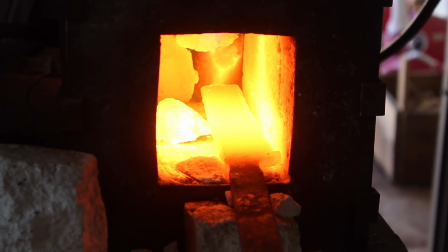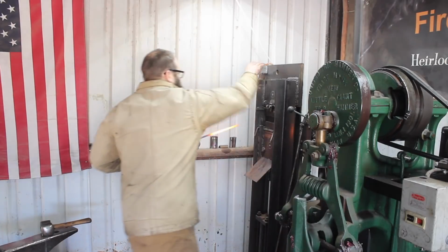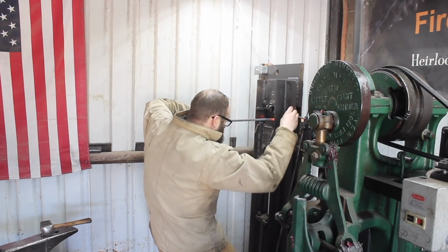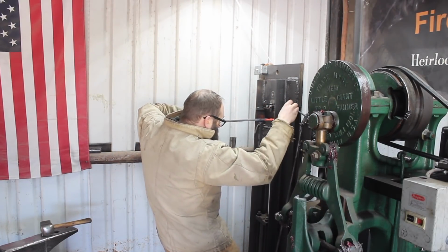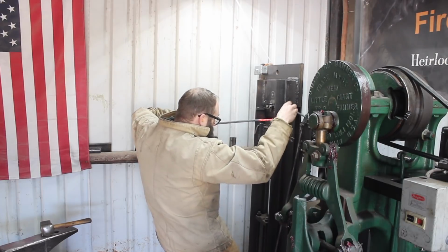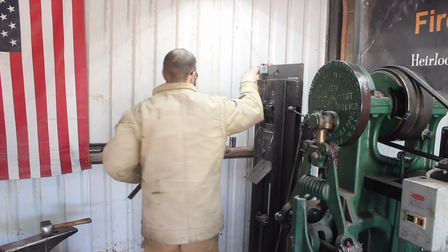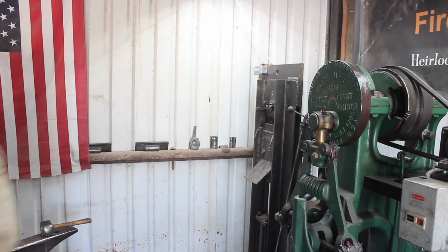I had enough material left on this billet here that I welded it up all the way around, sealed it up, and now I just threw it in the forge. I'm just going to cook this thing. We're going to bring it up to the melting point of copper. We're going to see if we can actually get a good bond on this billet.